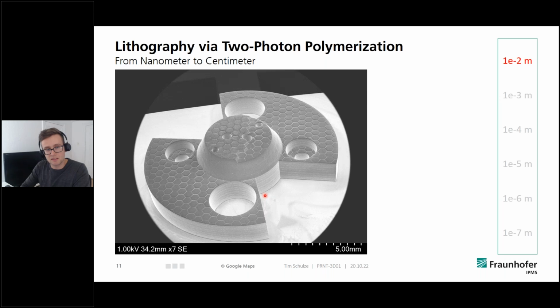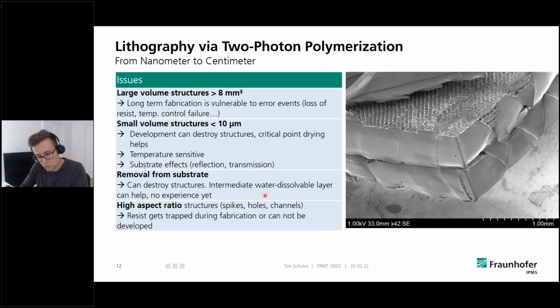And on the other hand, it's also important to really get some experience with all the issues this system could have. Something you need to consider when printing structures. For instance, if you have very large structures and long printing times, various things can happen. Usually the objective is always inside of the resist, but if the structure gets too large, it can sometimes happen that the objective loses touch to the resist, and then it's not illuminating light in the resist anymore, but in free space. And such things need to be considered when printing, and just need some experience.